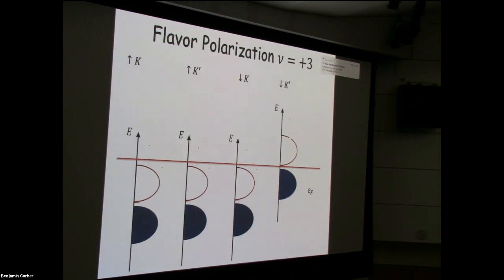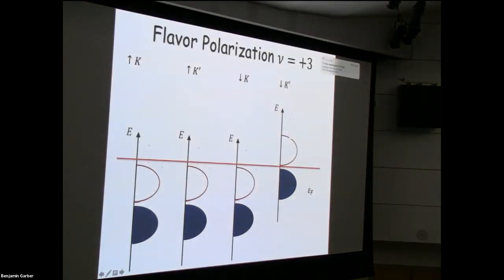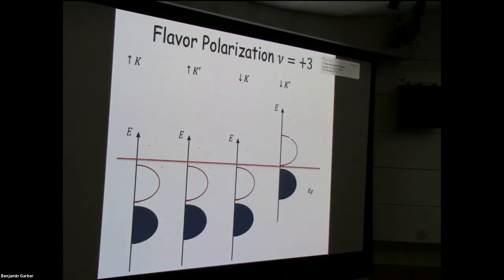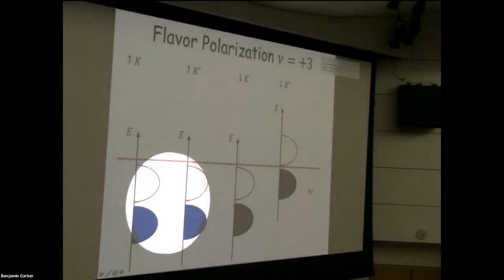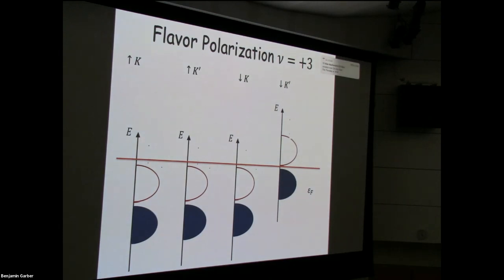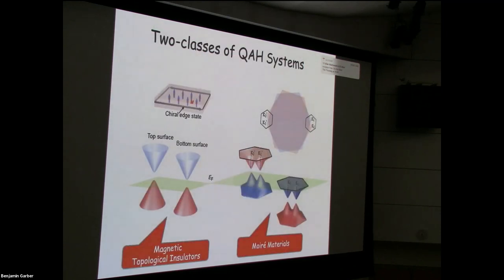in the moiré superlattice. So this is a cartoon of the electronic structure for the quantum anomalous Hall effect observation. An insulating state at filling factor three. Three of the four flavors have completely filled bands. One flavor is neutral. You can put the Fermi level in the gap, and these bands tend to be topological, have non-zero Chern numbers. And as we learned from David Thouless, one of the most charming things that I ever learned in physics is that a topological index of two-dimensional bands is actually not only observable, but the easiest possible thing to observe in a two-dimensional electron system. God was kind to us on that one. And here we see that time reversal symmetry is broken. So this quantum Hall effect and broken time reversal occurs even without a magnetic field.